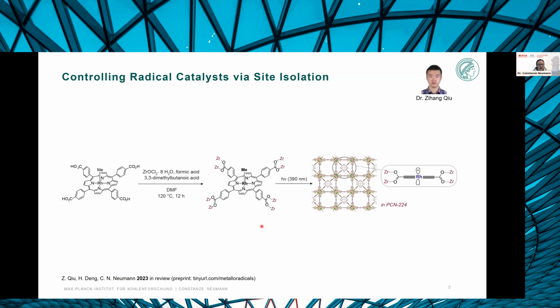So we figured that in order to access rhodium-2 metalloporphyrins in a metal organic framework, one good strategy synthetically would be if we made a rhodium-3 methyl complex in the MOF, because it is known from homogeneous catalysis or chemistry that you can split the rhodium carbon bond using light, and the only molecule that's released here is methane, which means that that would translate potentially very nicely into a MOF system because you don't generate any problematic side products.